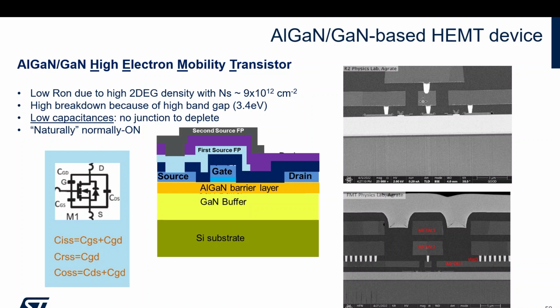The result of this is that here is just to show some of the structures that we have already fabricated. It's, I would say, a standard flow, taking into account some main differences in the case of GaN that are important, which I will mention in a moment. Again, let me argue about the reason, because this stuff is very worrying, because you have the epitaxy, which is a heteroepitaxy with a lot of threading dislocations. You have a lot of surface. This is a lateral device. So the status of the surface, if you have traps at this surface, is affecting the dynamic performance and static performance of your device. So it's really a pain, let me say.